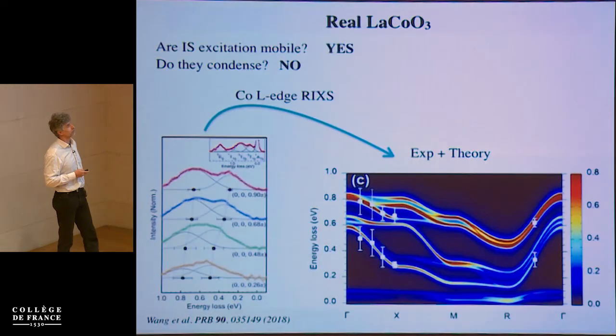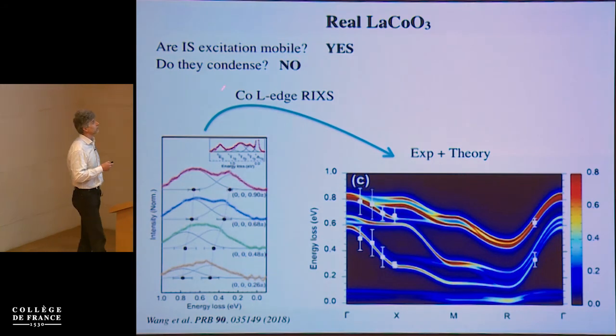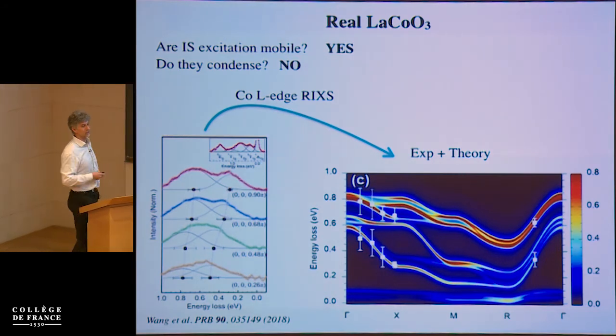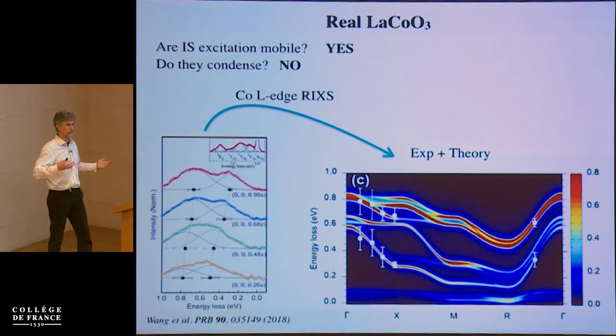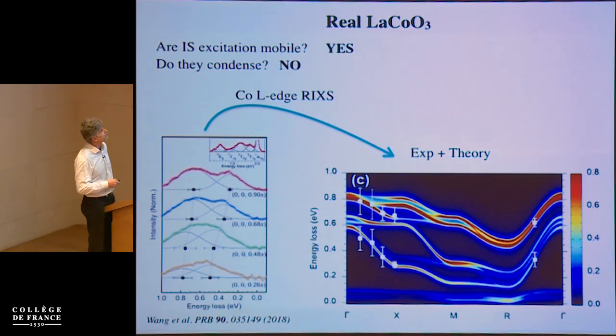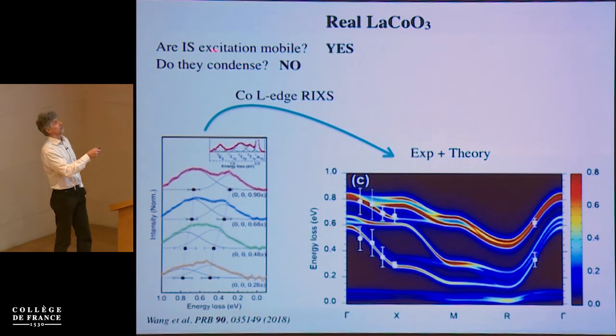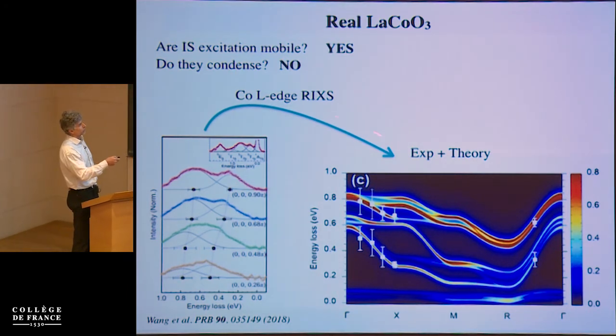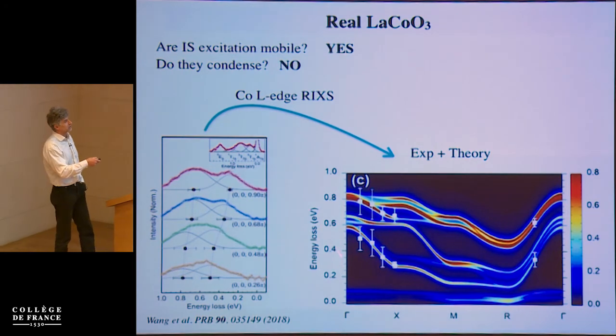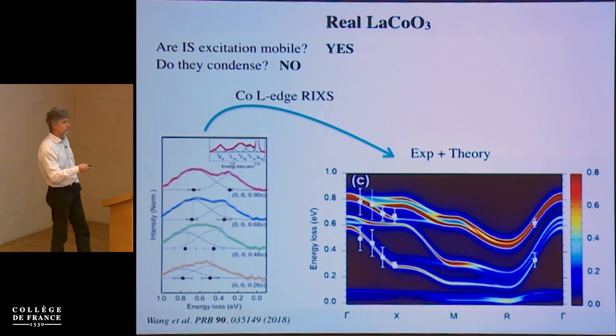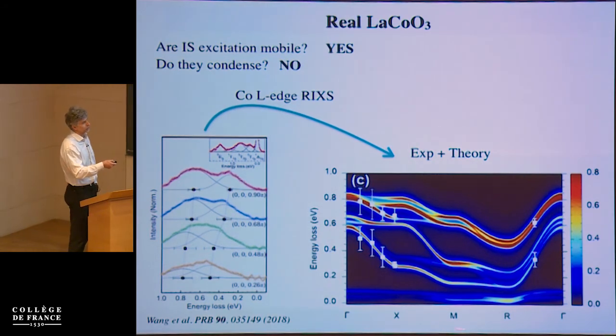Now, what about the real lanthanum cobaltate? Is there an excitonic condensation? The answer has been known for a long time: no one observed it. But the other question is, are there mobile excitons? This is a very new result, where using the RIXS technique, our experimental colleagues were able to indeed map out this rather steep dispersion in this part of the Brillouin zone.